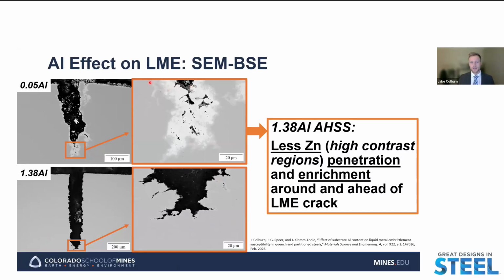Notably, what we see here is that there is a greater degree of zinc enrichment penetration in the low aluminum alloy when compared to the high aluminum alloy. This lighter contrast is again going to be indicative of higher levels of zinc in that area, and this was confirmed with the EDS. But that higher contrast region is not really seen as much with our high aluminum alloy as compared to the low aluminum alloy. This is potentially indicative of the relative amount or availability of zinc during testing here, potentially having higher levels of zinc availability in the low aluminum alloy as compared to the high aluminum alloy.